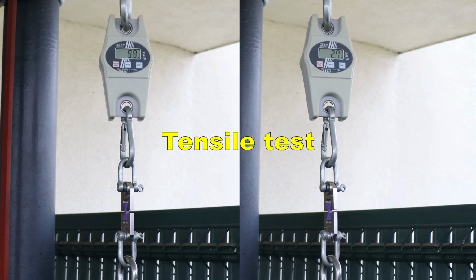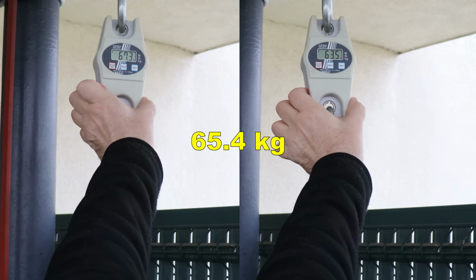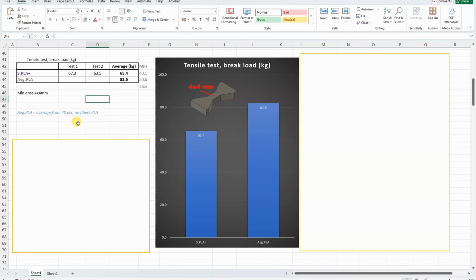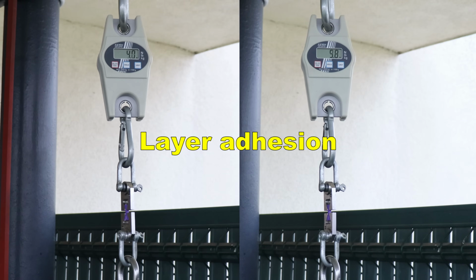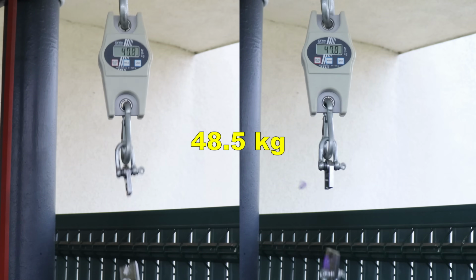Tensile test with horizontally printed objects. I already mentioned that I will include here the result for average PLA, which is calculated from 40 pieces, no fibers PLA. And we can see that this average PLA is stronger by approximately 26% compared to the Super PLA Plus.